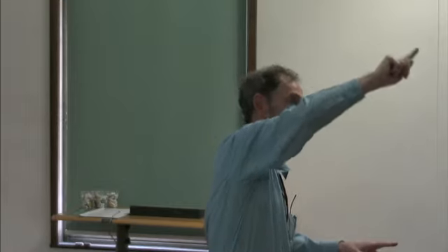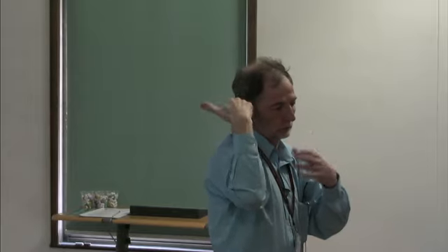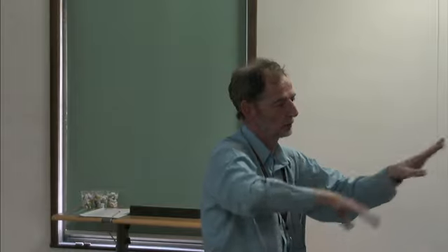Then they plotted the hysteresis against the middle eigenvalue, and they found an incredibly sharp cusp like this. So this was the first thing that they did, and very, very sharp. There are some theories which predict the shape of this cusp based on the tradeoff between interfacial and macroscopic elastic energy. Then they did these more sophisticated things to try and get the cofactor conditions to hold as well.